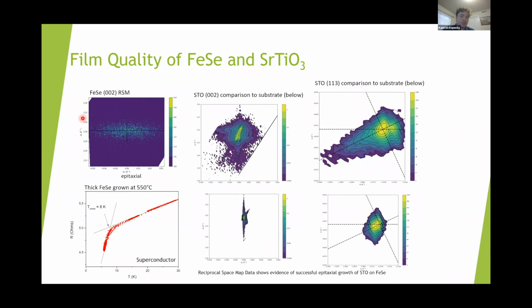From there, reciprocal space mapping of the 002 iron selenide peak confirms further epitaxial growth, as do the symmetric scans from the theta-2theta. The thick, bulk iron selenide layers show a critical temperature onset at 8 Kelvin, which is consistent with literature values for bulk systems. And then reciprocal space mapping of the strontium titanate 002 and 113 peaks confirms that there is epitaxial growth of the strontium titanate on top of the iron selenide with respect to these substrate peaks down below.